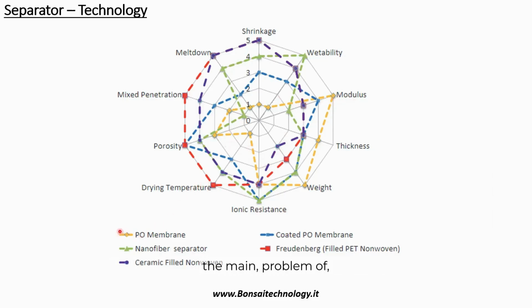The main problem of the polyolefin membrane without ceramic coating is that it's very sensitive to the temperature. Okay. As you can see, the score for shrinkage, meltdown, and drying temperature is very, very low. And the reason is because there is no ceramic coating layer that increases the resistance at the temperature. Okay. So this is the reason why many players are moving from PO membrane without ceramic coating to PO membrane with ceramic coating.